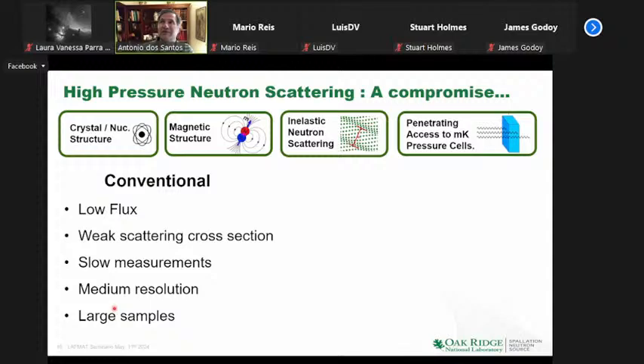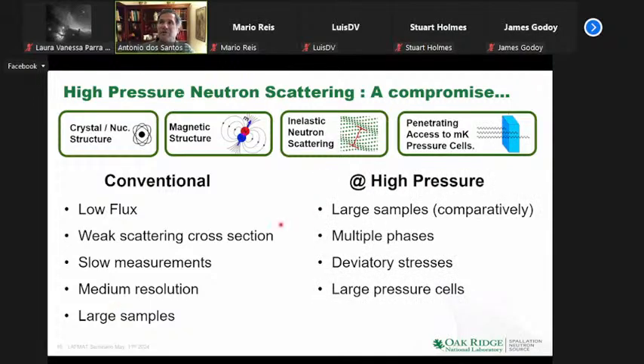Although this is the caveat, when you start adding high pressure, because you need large samples, you can't go to such high pressure, and because it's so intimately coupled with the pressure cell, often in your data you see the signal from multiple phases from the cell body, from different sample containers. At these large samples, it's very difficult to get truly hydrostatic, so you often lose sample quality from deviatoric stresses, and you require large pressure cells, which are both expensive but also take longer to cool and to heat up or to warm, and so it makes these experiments really challenging.